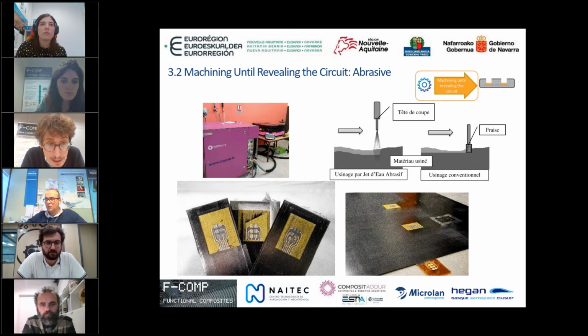It is not completely smooth, because as you can see in the explanation in the image on the top right, compared to the conventional machining, this introduced just a delta of the thickness machined. And so this means that if we don't have a completely flat reference surface, we are going to transfer those irregularities to the final part. And you can see in the image in the bottom left that there are some parts that are completely revealed and other ones that still have some carbon, that is the black parts. But in any case, the solution is promising. By adding some additional copper plates, for example, in the sensor at the initial phases, this kind of solution could be improved.